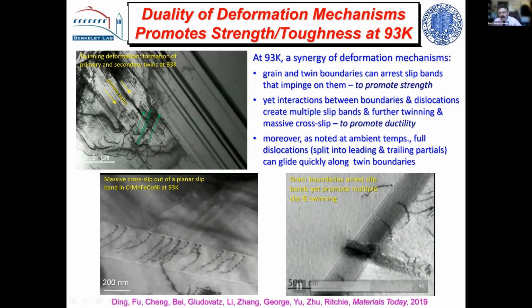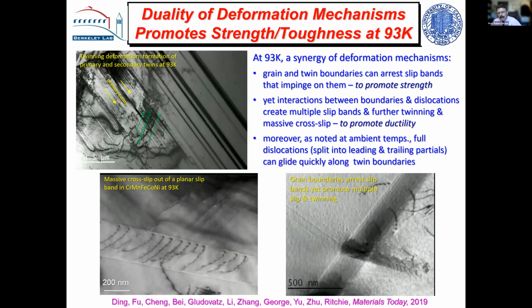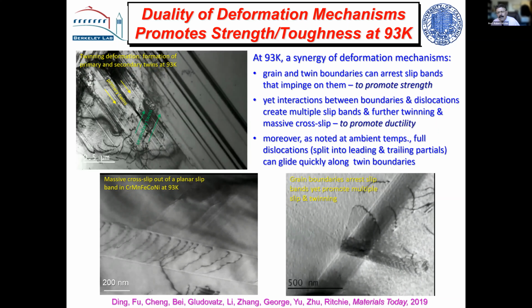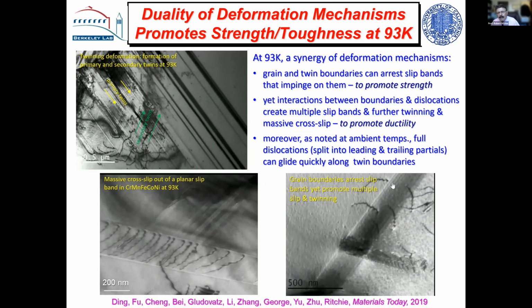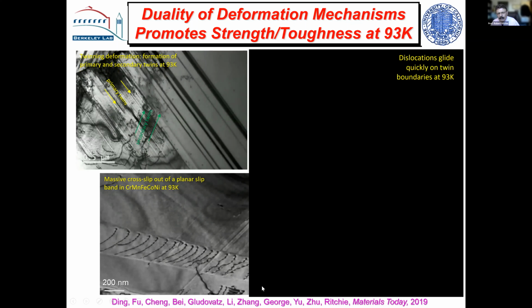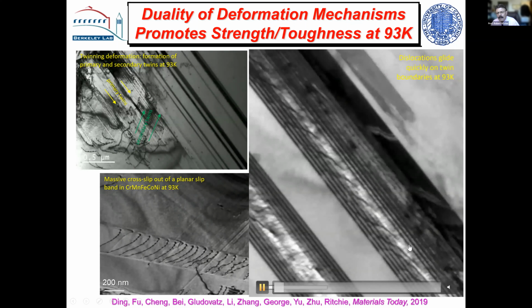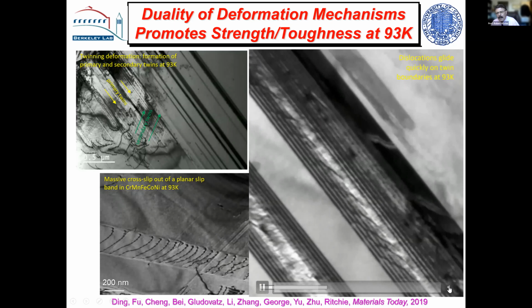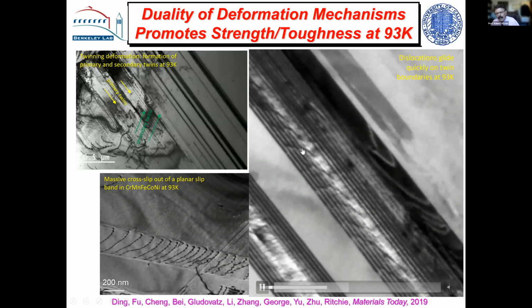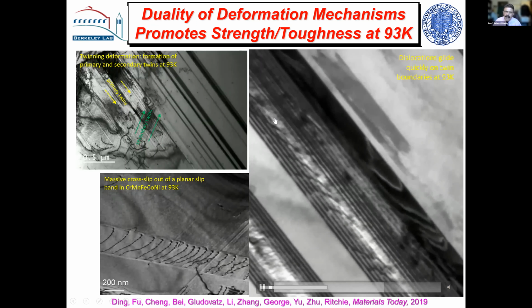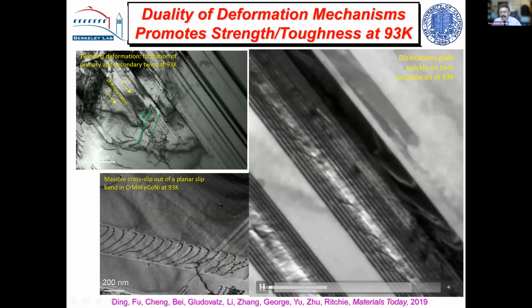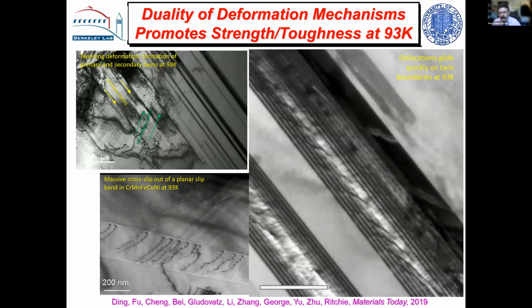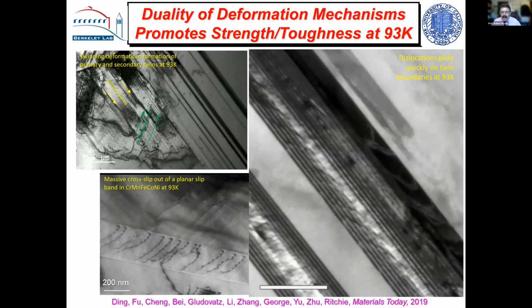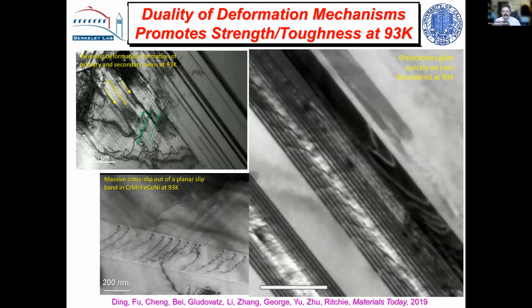So again, we have mechanisms that promote and mechanisms that inhibit dislocation motion. And the last one I think is very interesting is the motion of these dislocations along the twin boundaries themselves. This is a twin, and you can see these partial dislocations moving down these highways. So again, this is one of the mechanisms by which you can promote deformation. Very, very interesting.